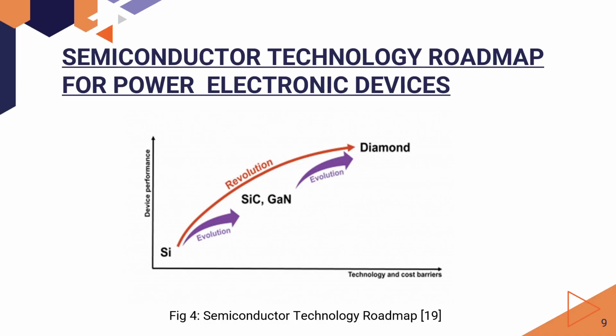Semiconductor technology roadmap for power electronic devices. This figure shows the semiconductor technology roadmap. It is critical for future diamond-based active devices to have a wafer size of at least 2 inches and a defect density of 100 cm^-2 or less. Various approaches to producing freestanding wafers from thick diamond films are being researched. A mosaic type method is now approaching 2-inch wafer size, but defect density must be reduced. According to the Yole single crystal diamond wafer technology roadmap, low defect 2-inch wafers would be commercially available in 2016 to 2022.